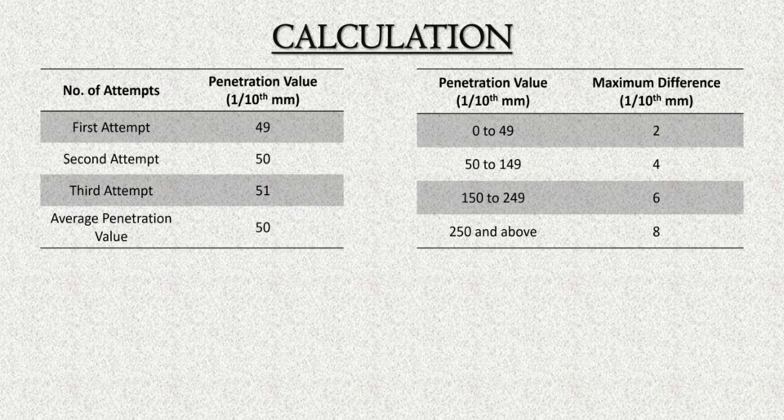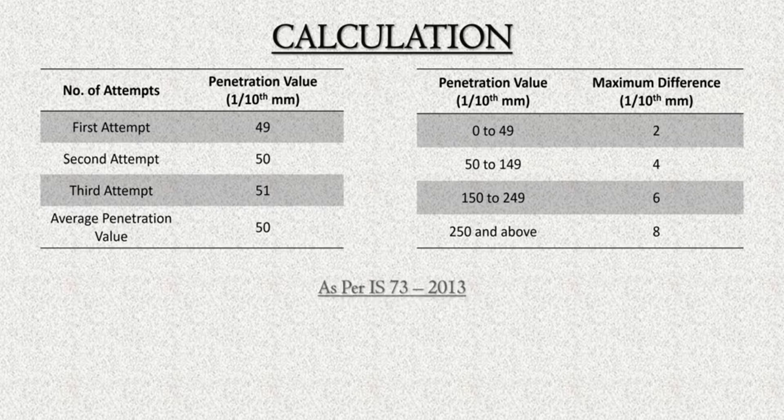Maximum difference in penetration value: 0 to 49, maximum difference is 2. 50 to 149, maximum difference is 4. 150 to 249, maximum difference is 6. 250 and above, maximum difference is 8.